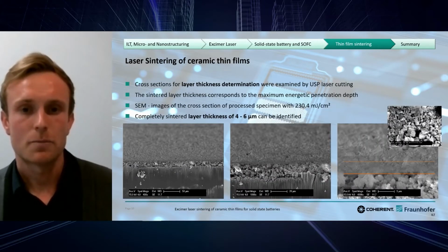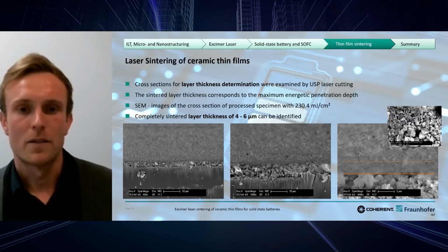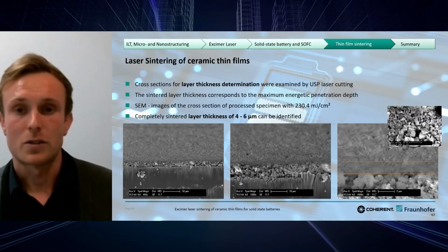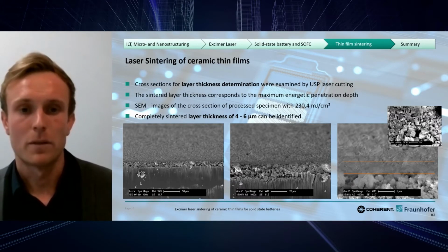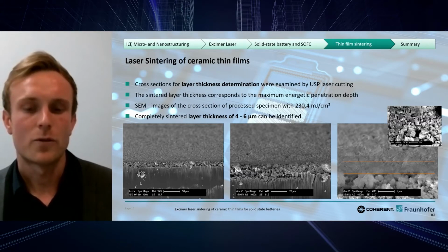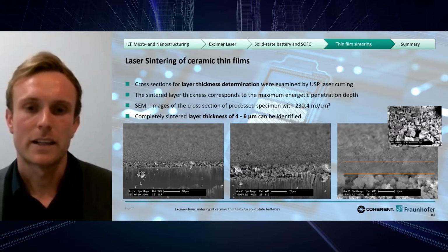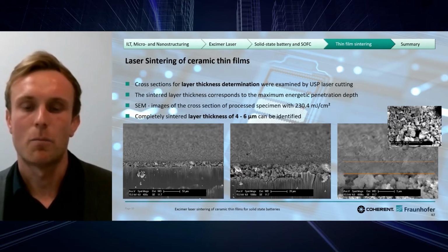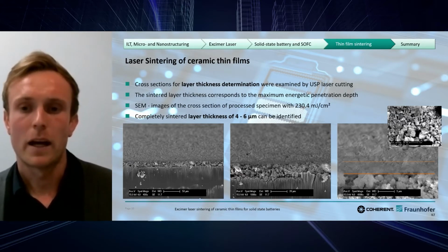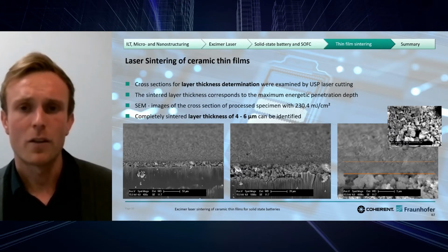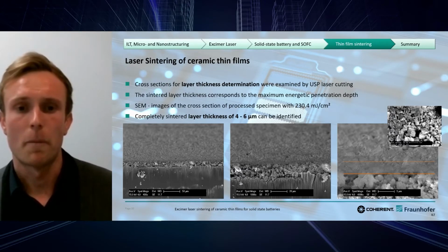Another look should be taken at the layer thickness, because with that we can determine the maximum penetration depth. So this is the depth beneath which the material will not see any light, any energy, any thermal damage. And here you can see three cross sections of the same sample. On the right-hand side, you can see that the layer thickness of the sintered material is between 4 and 6 micrometers. So that's pretty small and pretty good, thinking of the requirements mentioned before.